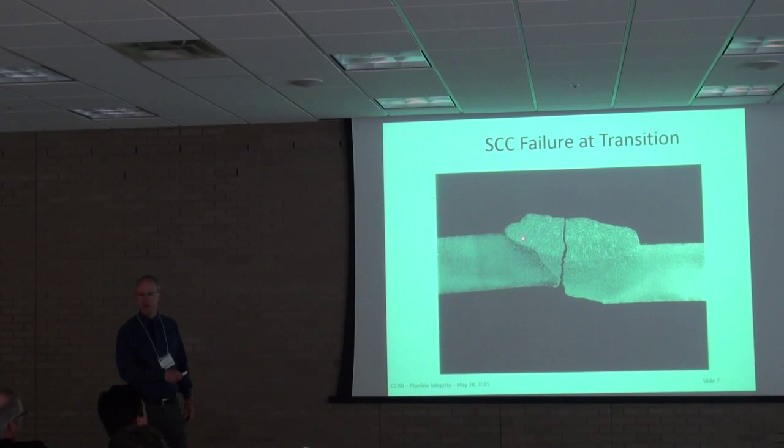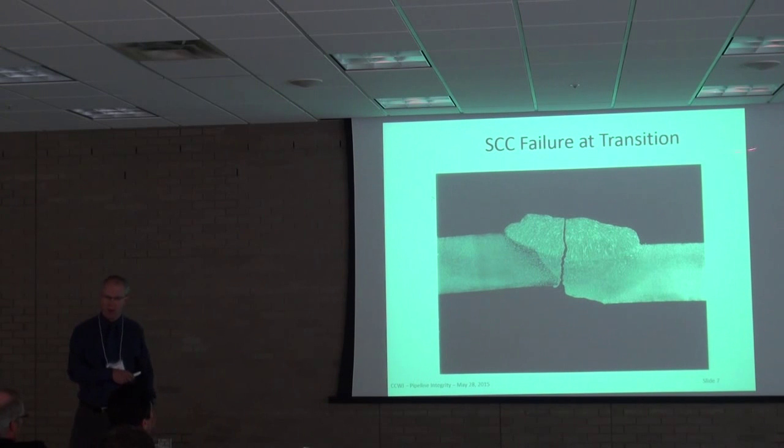I'm certain there must have been some NDT on it as well, but obviously it got missed. So there's nothing wrong from a hardness point of view, but once you concentrate the stress, with bad quality control and bad fit up, you end up with a catastrophic failure.